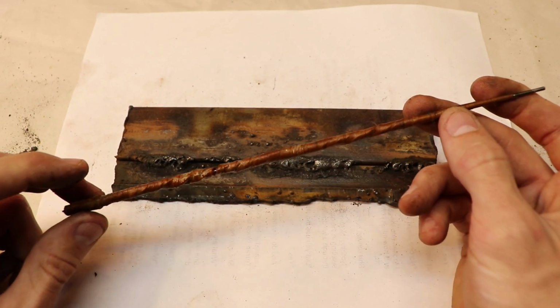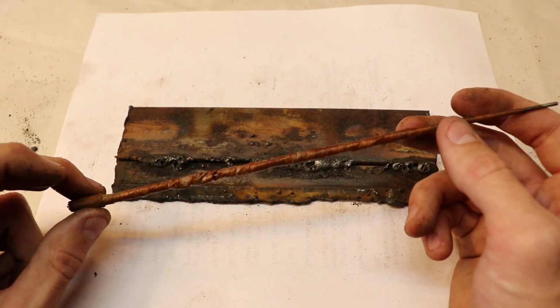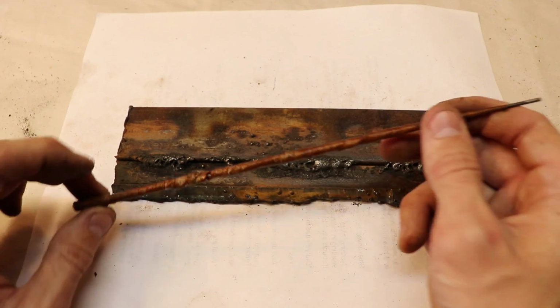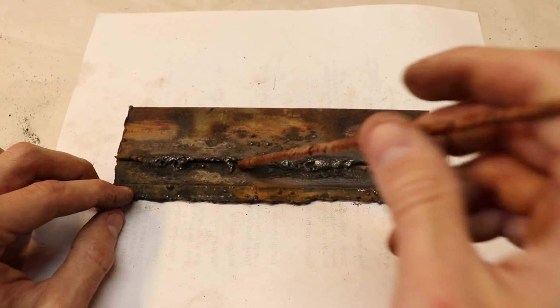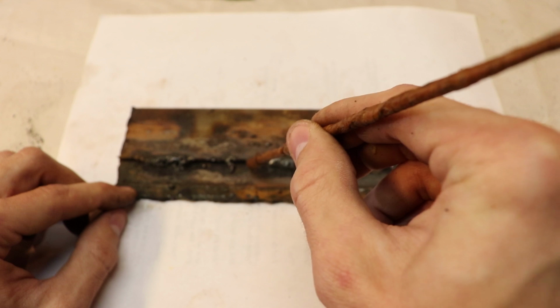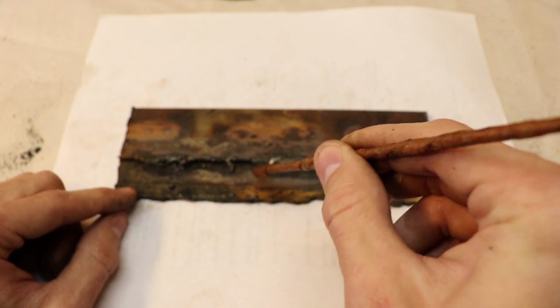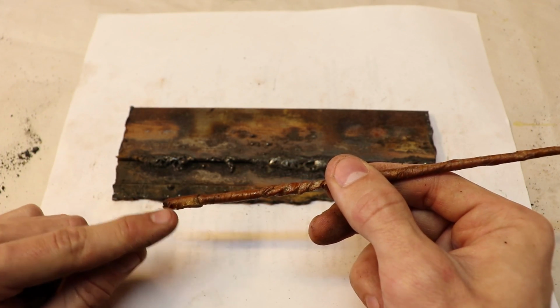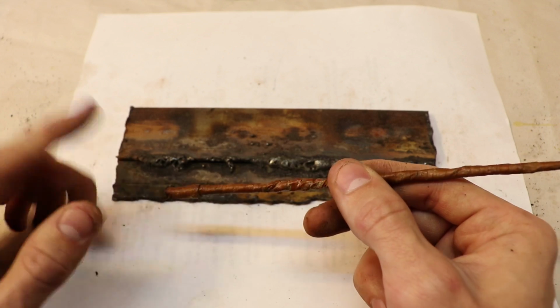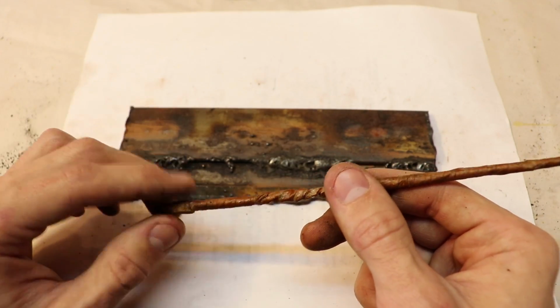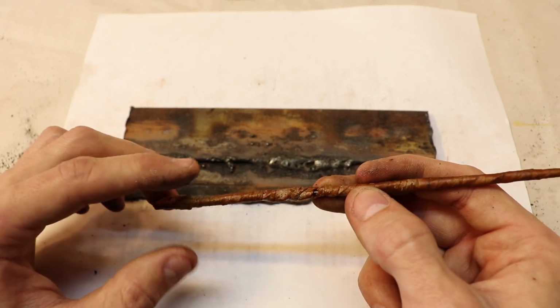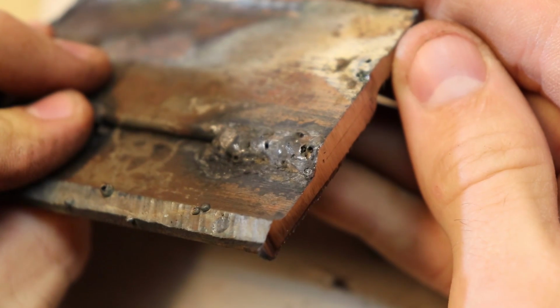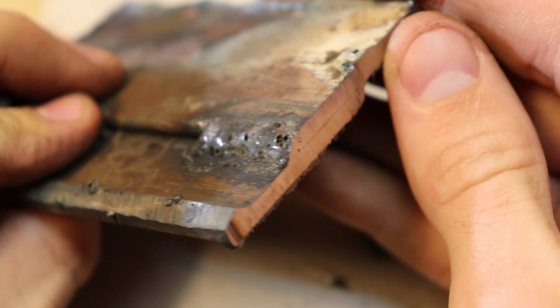I noticed with the thicker wrapped rods that it was harder to get them into the joints because I had to push into the joints more with a bunch of unburnt paper in the way, and this stuff doesn't burn off quite as easily if you have a thicker wrapping of it. So this is from the sodium silicate rod.